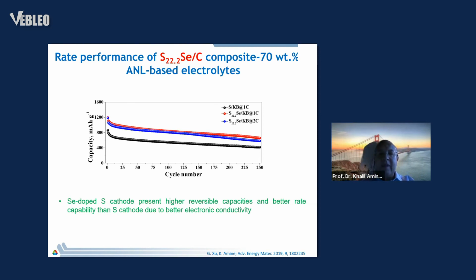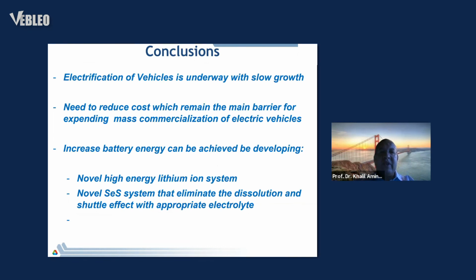So my conclusion to you is electrification of vehicles is underway with slow growth, and we need to reduce cost, obviously. If we do that, then there is an opportunity for massive commercialization of electric vehicles. I have shown you a few examples of developing the next generation lithium ion to get us to that 350 watt-hour per kg or higher. And then this new system, which is still low cost, selenium sulfur with new electrolyte, at least we overcome the conductivity and the dissolution and the shuttle effect that are among the main barriers to enabling this system.